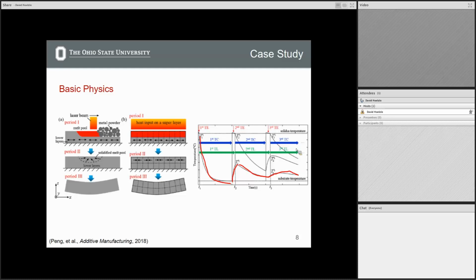I will make a note: when we talked about layers here, we were looking at a very computationally efficient means of computing this, and so our layers were a pseudo layer. It was much larger than the layer you get in each recoating operation. So this is on the order of around 1 millimeter, where usually the layer is on the order of, say, 50 microns. Yes?